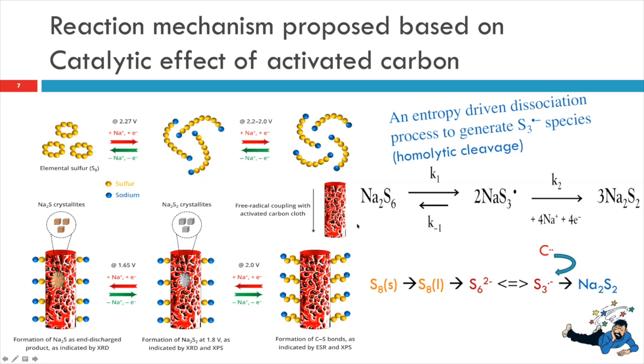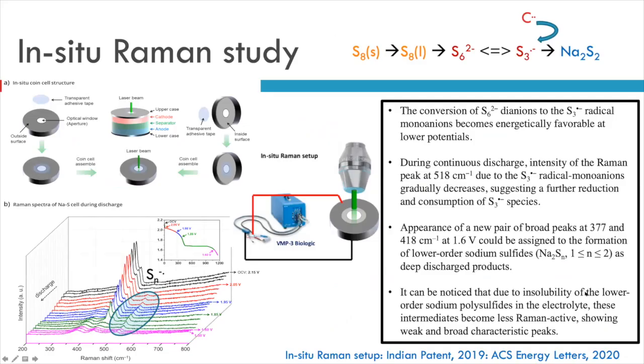the carbon host, and that restricts the sulfur polysulfide dissolution, and further also catalyzes the reaction, because we are not allowing polysulfides like S6 to go to the lower ones. Immediately it goes from here to sodium disulfides. So this is the observation we have found, and then we'll show you by different experimentations what we are saying. It is actually shown in the experimentations.